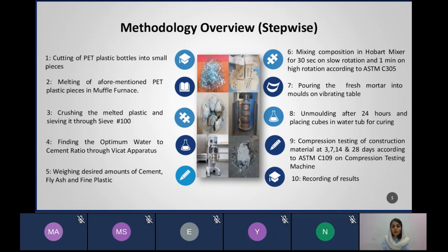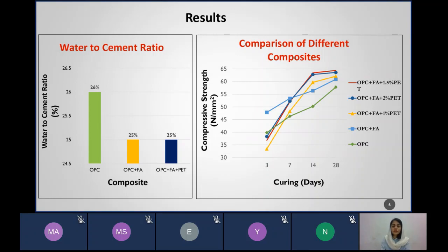Then I poured the freshly made mortar into molds. I left them for 24 hours and the next day I unmolded them and put them in water for curing. And then I performed testing on them. The results that I obtained were, first, water to cement ratio. As you can see from the graph, the water to cement ratio of ordinary Portland cement was 26%, while that of cement and fly ash and cement, plastic and fly ash was 25%.